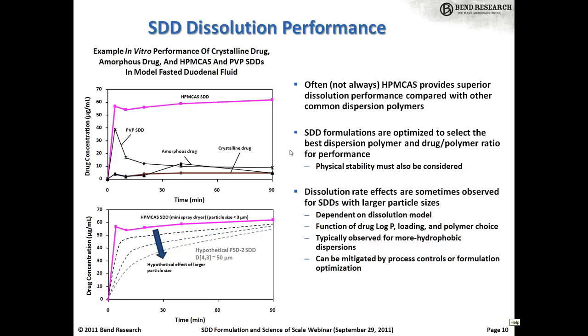So what you do, of course, during your selection of an SDD formulation early in development is select your polymer and your drug-polymer ratio to achieve this kind of performance: rapid dissolution and maintained supersaturation. Of course, in addition to performance, you also have to consider physical stability, which we'll touch on next. But there's typically a logistical driver to maximize drug loading in the SDD, so you typically want to increase drug loading as much as possible while maintaining performance.